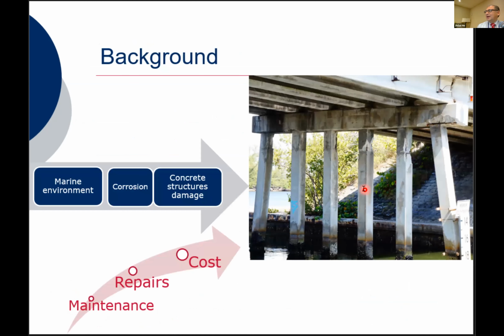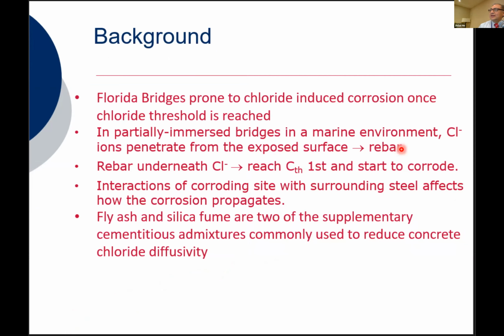Pierre already mentioned this slide, so I'm not going to spend too much time other than to mention that typically in a marine environment, we expect the splash zone to be the one with the worst corrosion. In this case, this is in the Intracoastal, right next to our campus, Dania Beach. For some reason, that didn't take place in there. But as he mentioned, you can see that due to chloride deposition, a number of piles as well as the cap are undergoing spalling. I should have included the picture from the other side because it's a lot worse than what you see on this side. But in any event, let me go to the next.